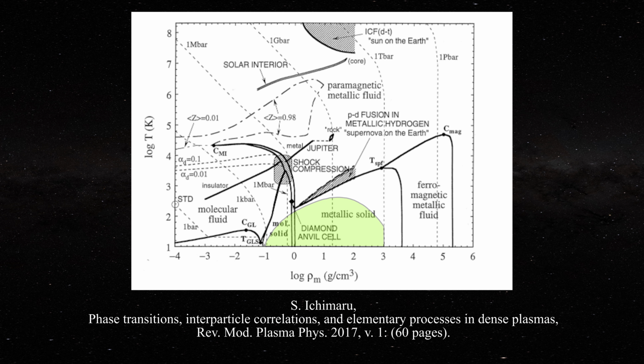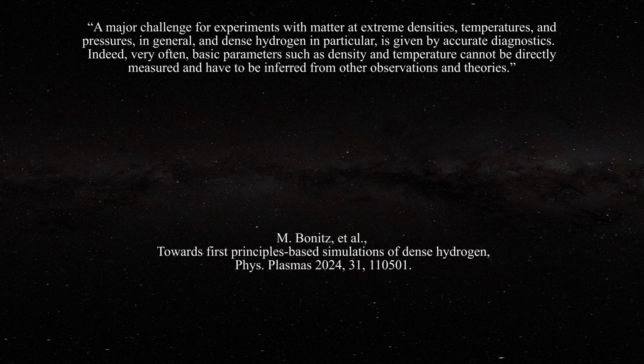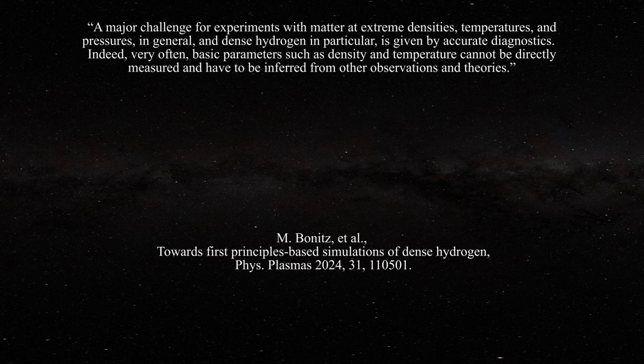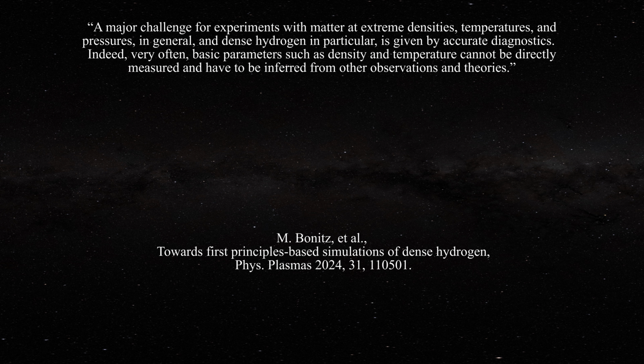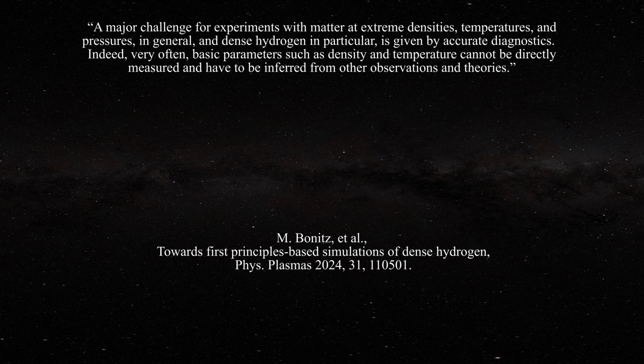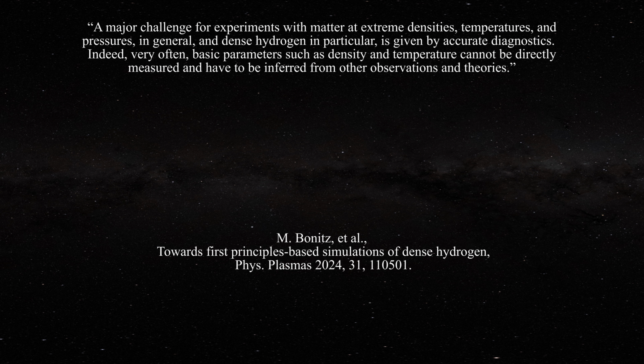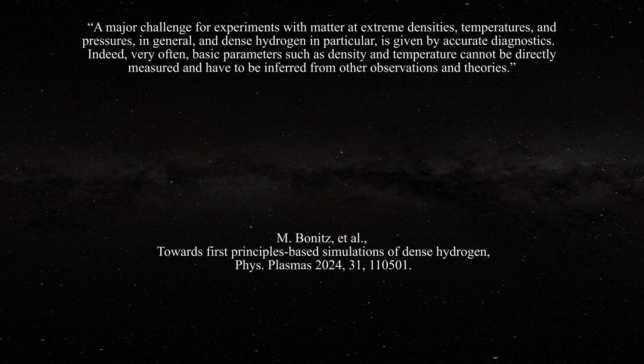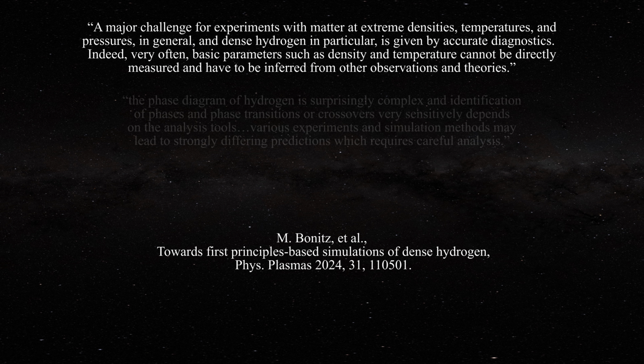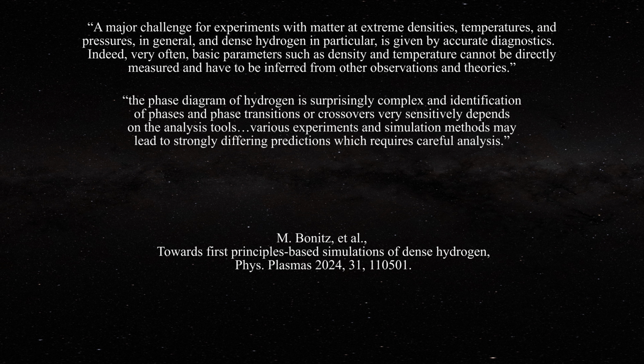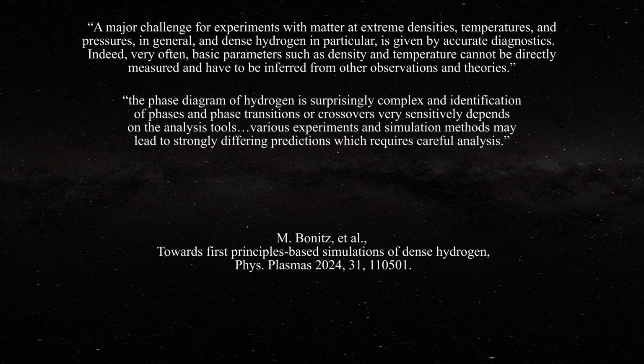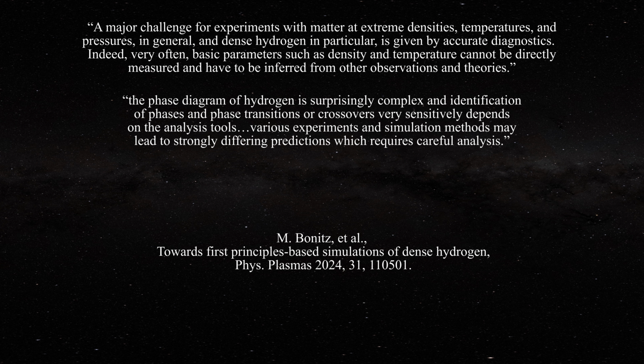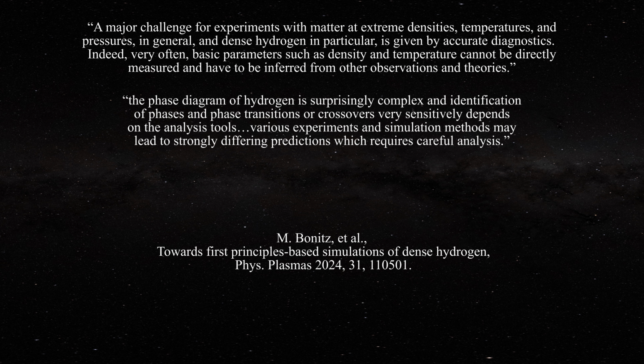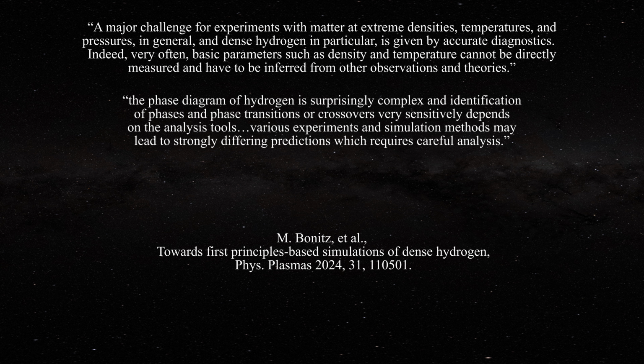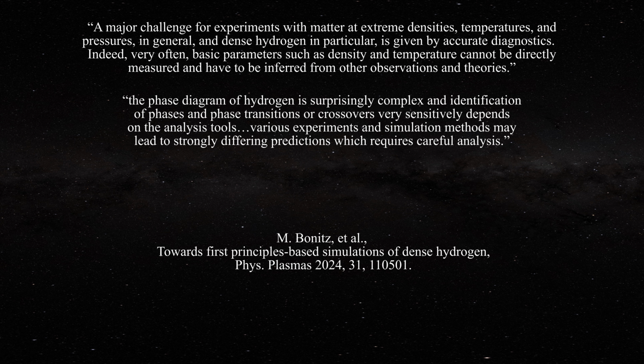Relative to establishing the correct phase behavior for hydrogen, it has been said that a major challenge for experiments with matter at extreme densities, temperatures, and pressures in general, and dense hydrogen in particular, is given by accurate diagnostics. Indeed, very often, basic parameters such as density and temperature cannot be directly measured and have to be inferred from other observations and theories. It has also been argued that the phase diagram of hydrogen is surprisingly complex, and identification of phases and phase transitions or crossovers very sensitively depends on the analysis tools. Various experiments and simulation methods may lead to strongly differing predictions which require careful analysis.